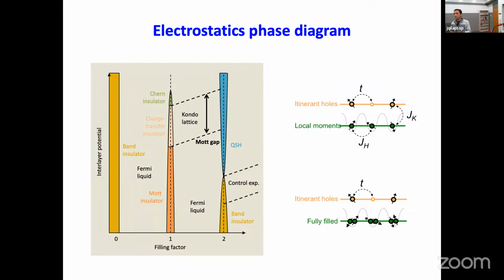Yeah. This is the cartoon, or is this like the middle line? Because when you increase the confining potential, at the same time that you're increasing U, you're also increasing the Moiré subband spacing. So you mean this electric field here? Yeah, so the filling factor 1 as a function of interlayer potential. Yeah. So in principle, it does more than just changing the interlayer potential difference. It may not change the U too much, but it probably changes the bandwidth of each band. Yeah, you change the bandwidth a bit more. You can change also the delta in that case.